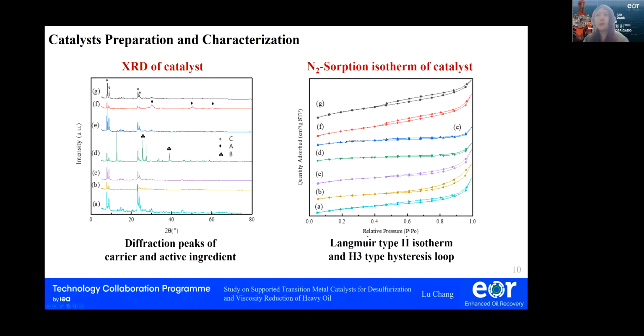And the XRD method tests the composition of the catalyst by detecting the diffraction peaks of the carrier and active components. And the N2 sorption isotherm indicates that the catalyst has a mesoporous structure.